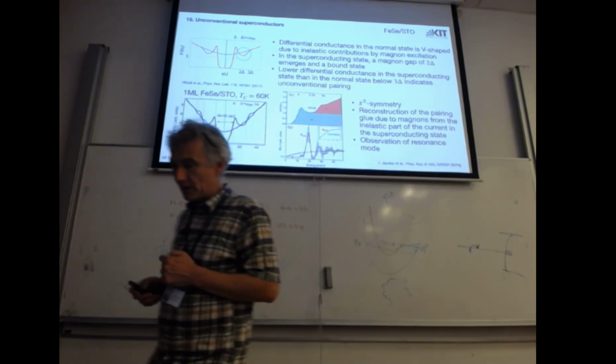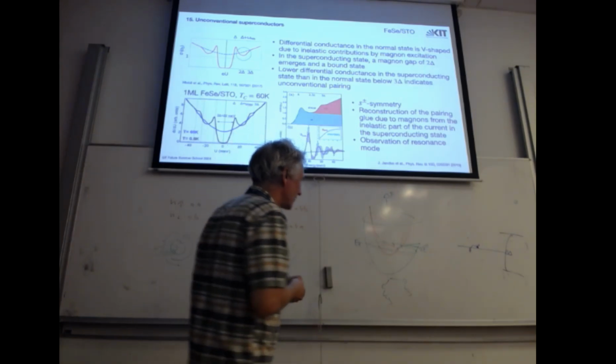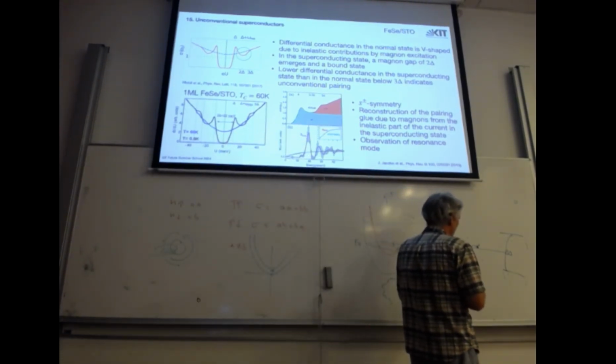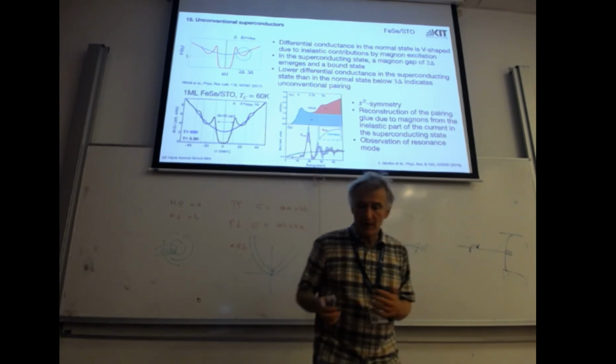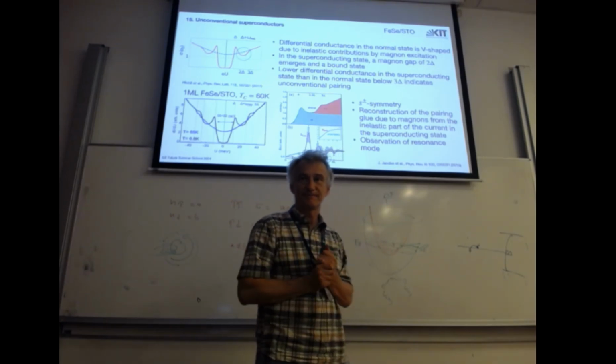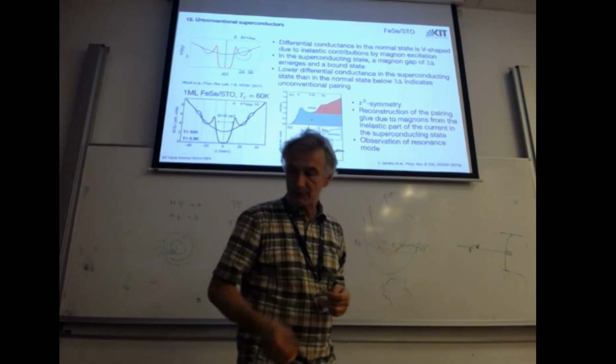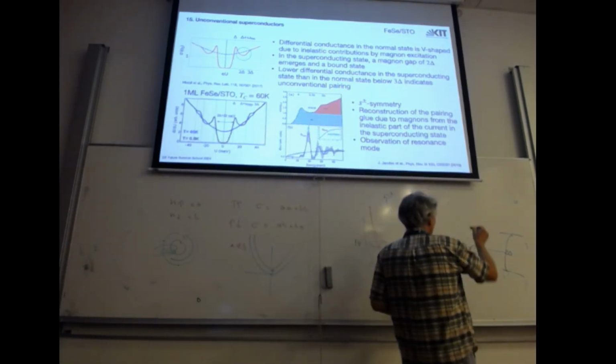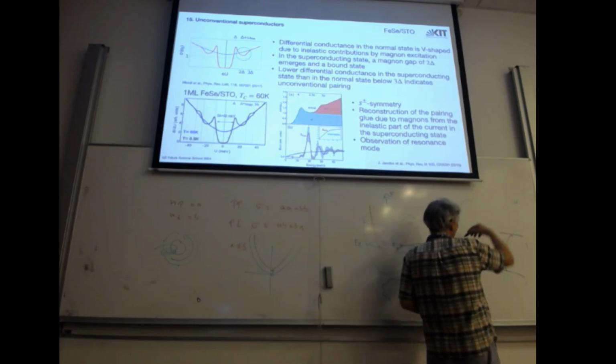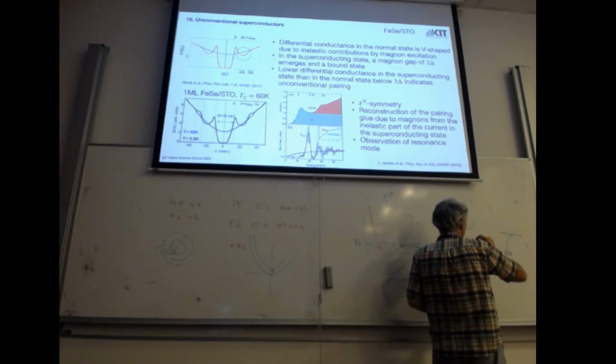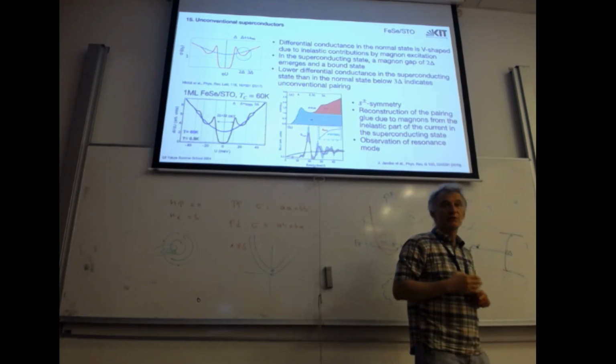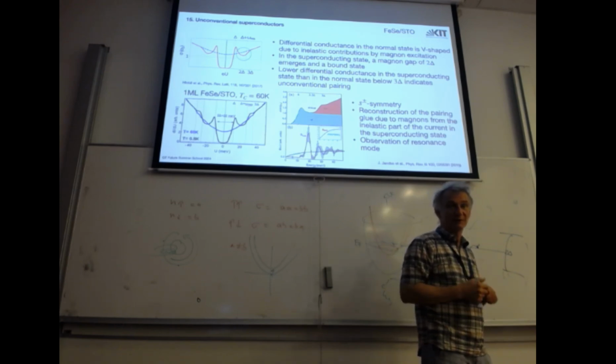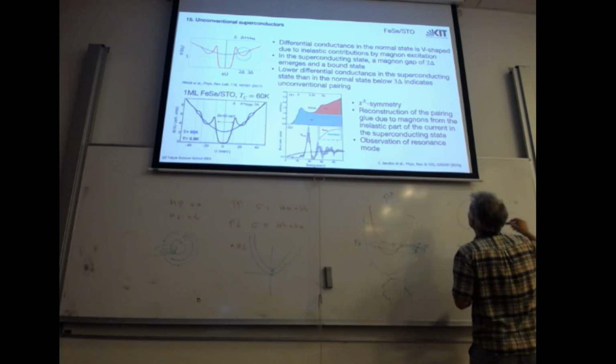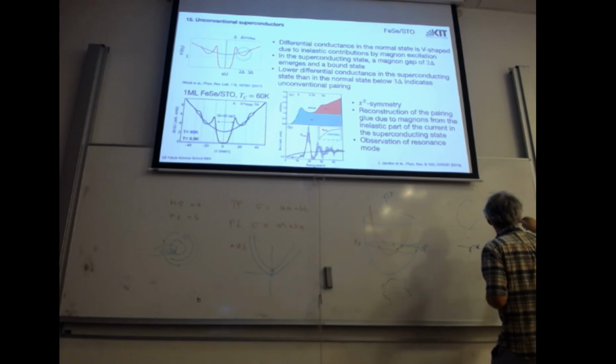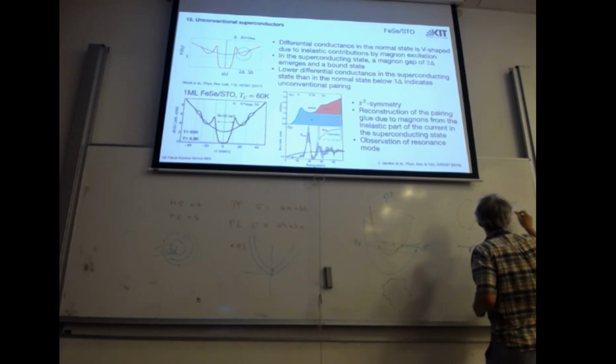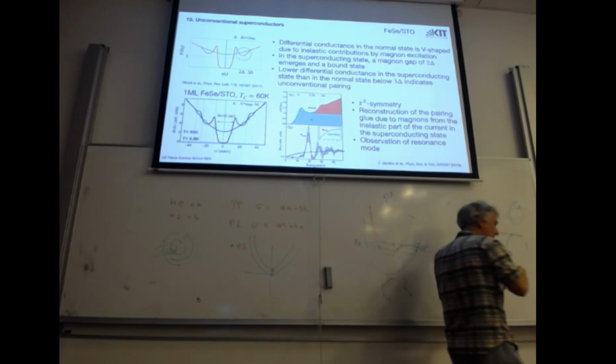That's where it is. But the side remark I want to give is that in this graph, if there's magnon exchange, we flip the spin. So if you think about the order parameter for the superconductor, if you have a single band, with phonons, you scatter from one part without spin flip, so you have an S-wave symmetry of the order parameter. And iron selenide has two Fermi surfaces, and you scatter from one band to the other with spin flip.